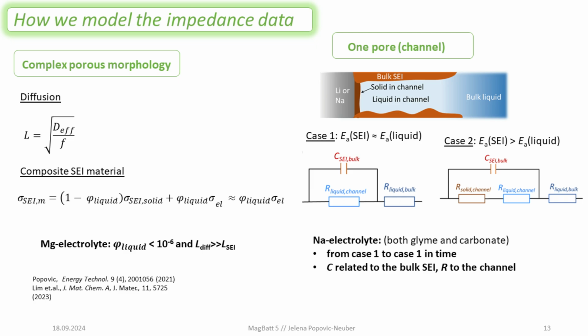On the other hand, we can just say, well, it's a liquid-solid composite material. For this, we had forever used our parallel switching model, where we have a total conductivity that is proportional to the conductivity of the liquid and the solid and their volume percents. In this case, the liquid is so much more conductive than the solids, orders of magnitude, that we can just approximate it with the volume percent of liquid and the conductivity of the electrolyte. And that gives us directly some estimate of the volume that we need in order to see liquid conduction, and that's very, very low in the case of magnesium electrolyte. So these are kind of two extremes.